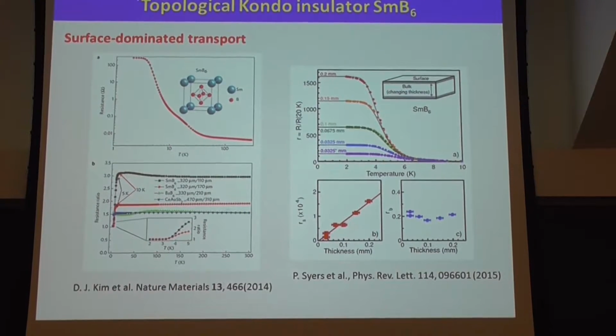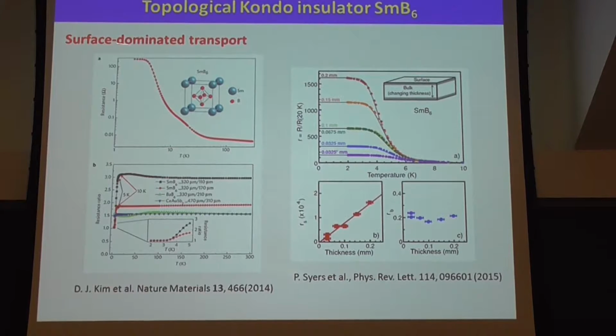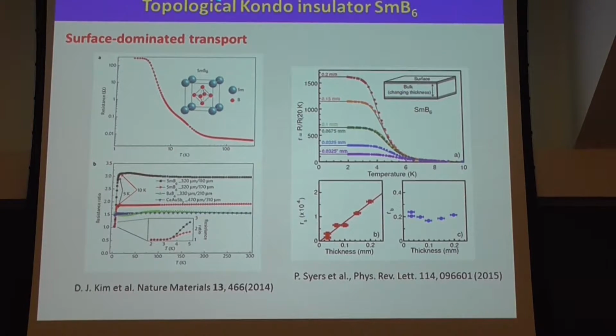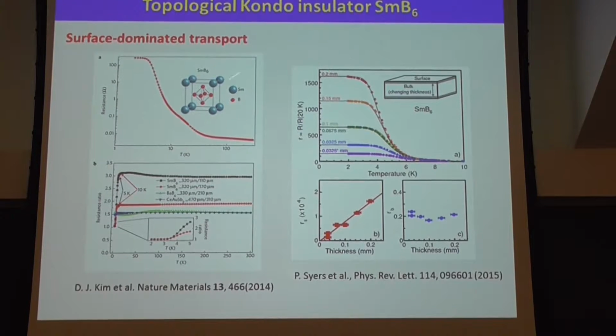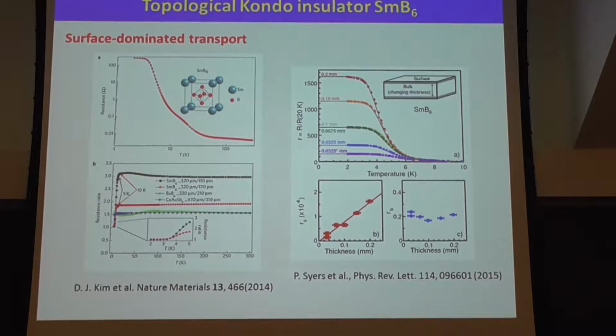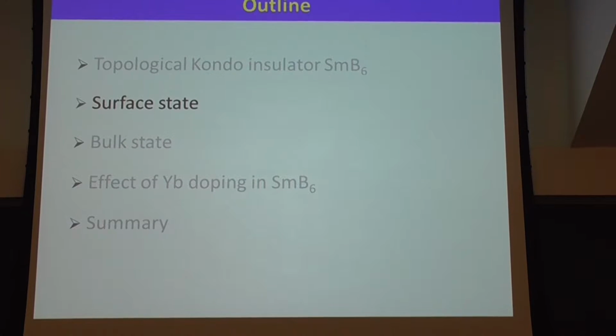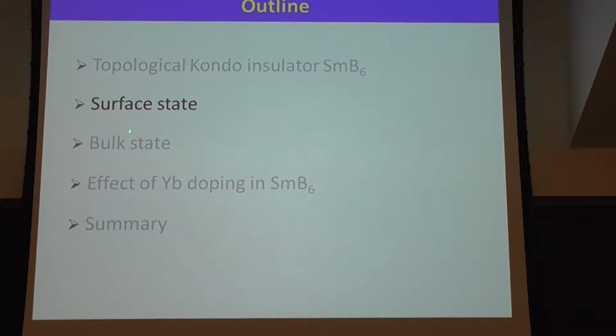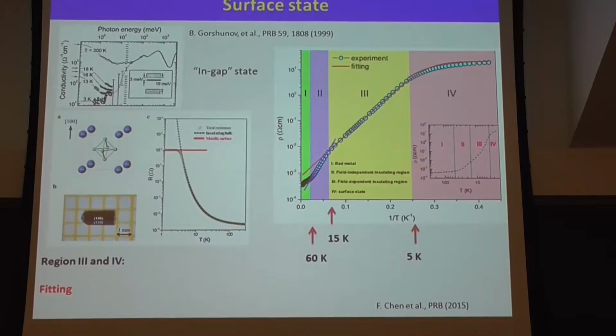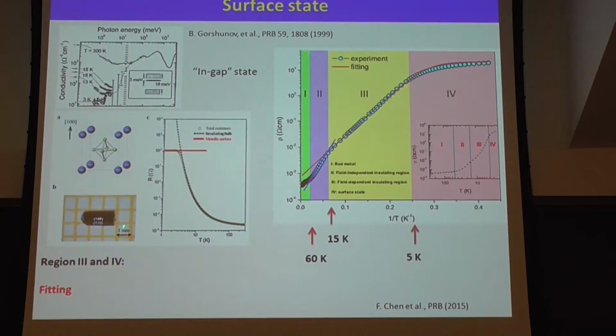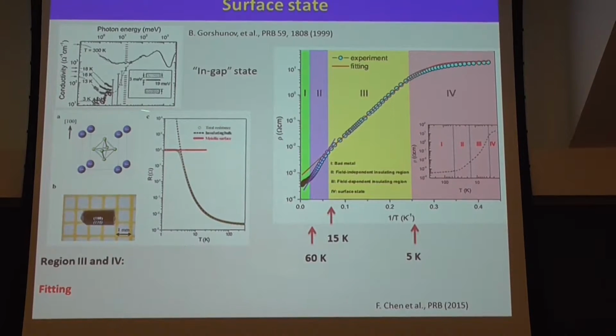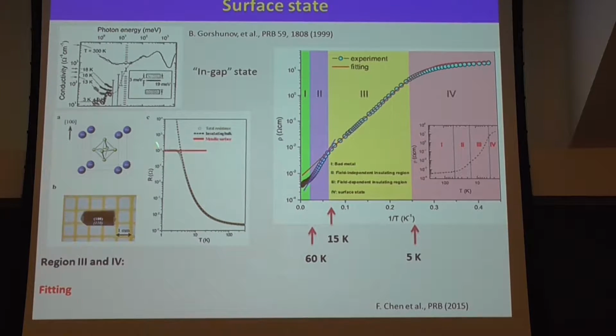Now there is a lot of evidence for surface-dominant transport in the topological Kondo insulator samarium hexaboride. As shown in the previous talk, no one can say so much about that. For the surface state, our group just uses transport. This is the data for a single crystal. We can measure the 100 surface and the 110 surface, and all show data like this. This is very beautiful data: below 4 Kelvin it shows the flat saturation.